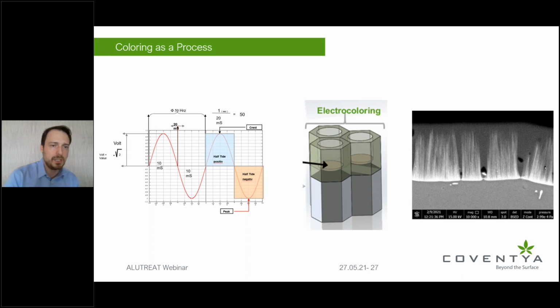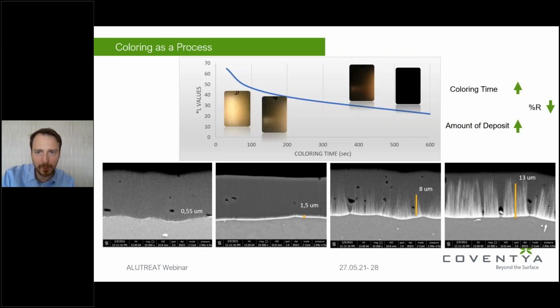The coloring, as a process, if we look more closely, is actually a very complex process. So we have our metal salts or metal oxides in our bath, and we are applying an alternating current to our template, to our aluminum substrate, and these metals start precipitating out at the bottom of the pores under the influence of this alternating current. And there is a battle, or constant balance, between the acidic solution that we are in, which tries to dissolve again the metal salts that we are precipitating in the pores, and the current that is trying to precipitate a higher amount, as you can see on the right-hand side, into the pores in order to change and adjust the color.